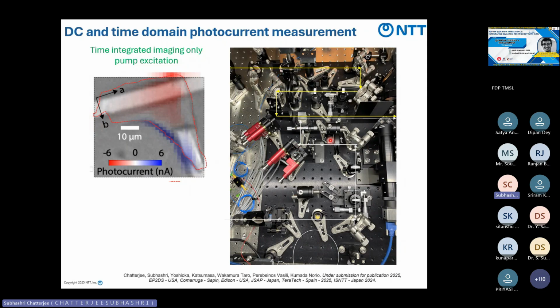We didn't use the probe, just to mimic previous reports. And indeed, edge photocurrent appears on the lower axis of our structure, with opposite photocurrent polarity appearing on the electrode, suggesting this is just because of maybe the photothermoelectric effect. But we are mostly interested in the edge part, what is happening at the lower symmetry.